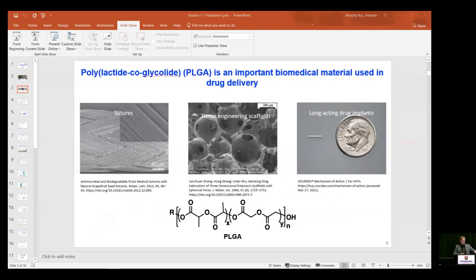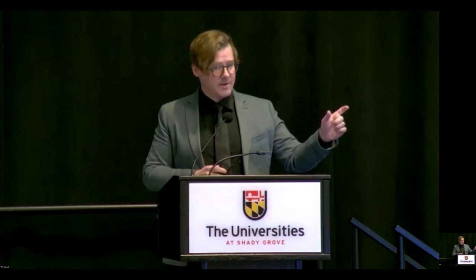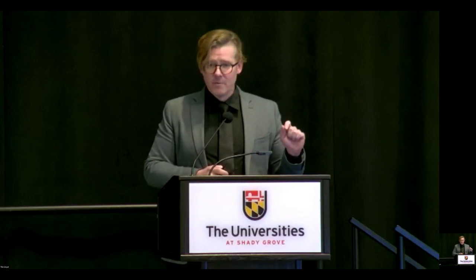Now we're looking at conversion of the copolymerization versus time separately for lactide and glycolide. Lactide is green, glycolide is blue. You'll see that glycolide, very early on, is incorporated in the polymer backbone and is essentially irreversible. So it goes to 100% conversion, whereas lactide adds more slowly, and it never quite gets to 100% conversion. What we can surmise from that is that the little cartoon at the bottom represents the sequencing in this polymer, where we have glycolide clustered near the chain initiator and lactide on the chain end. Okay, it's probably too early in the morning for this.